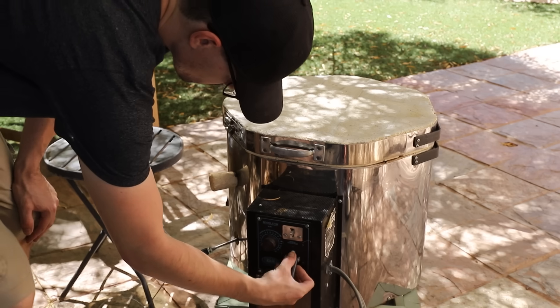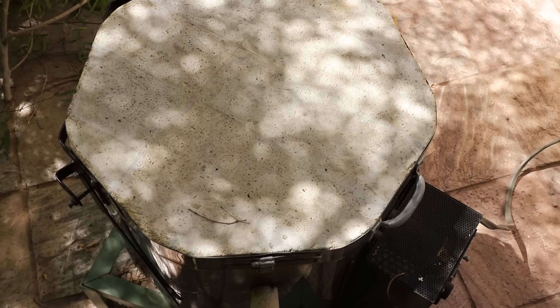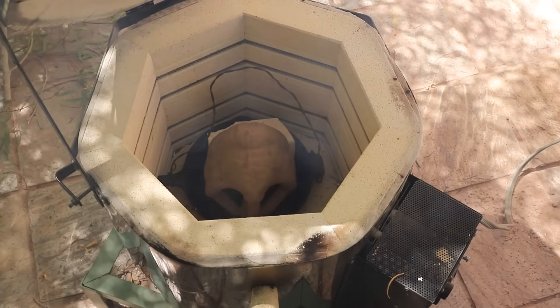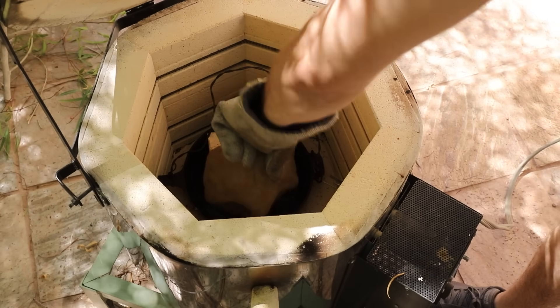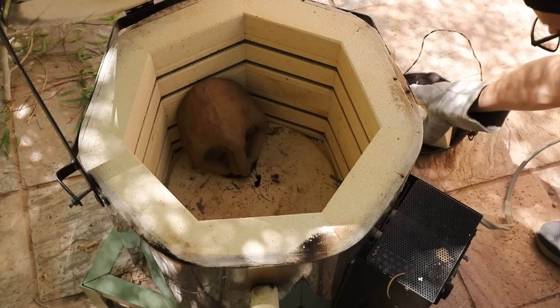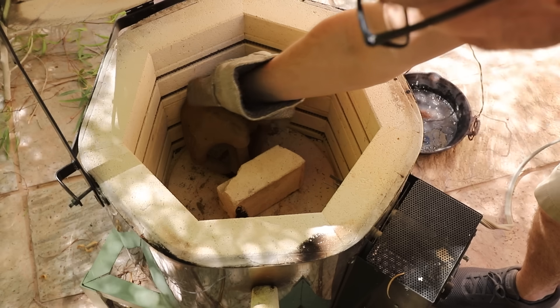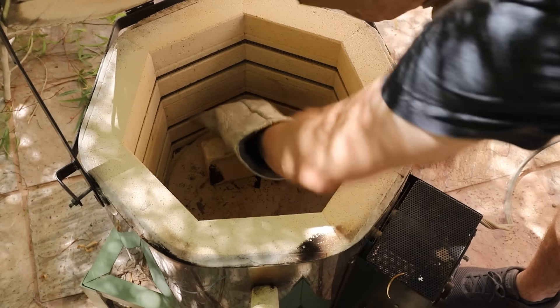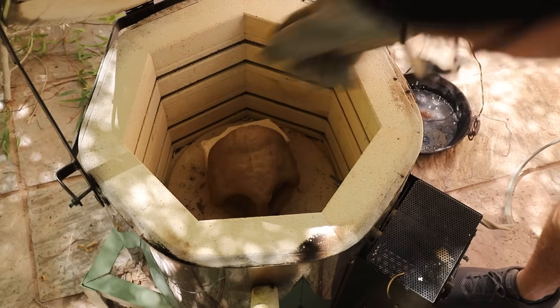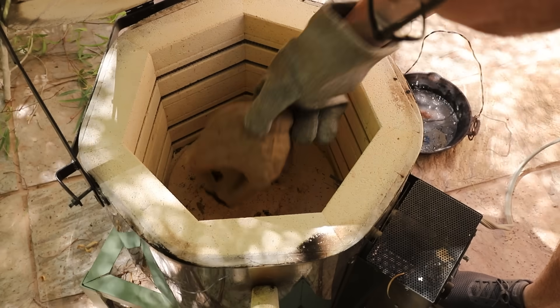Next I placed the shell into my kiln to melt out the PLA plastic. I set the kiln to about 500 degrees Fahrenheit, which is the temperature at which PLA will start to flow out of the shell. Once most of it had flowed out, I removed it and cranked the kiln up to about 1500 degrees Fahrenheit, which turns the shell into a really durable ceramic that will withstand the heat of molten bronze. For those who've been following my channel, I've had problems in the past with shells cracking during burnout — I think that was because I was using silica sand instead of fused silica sand. Ever since switching to fused silica I haven't had any problems with cracks.